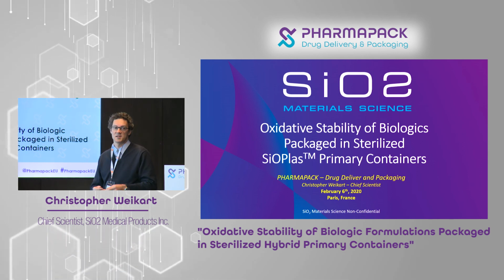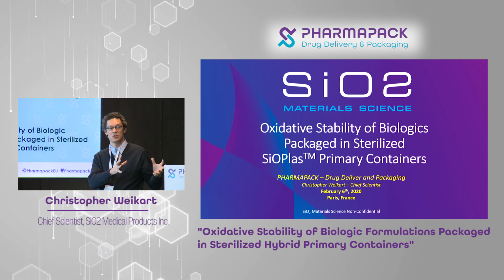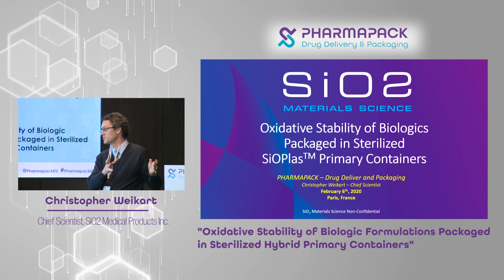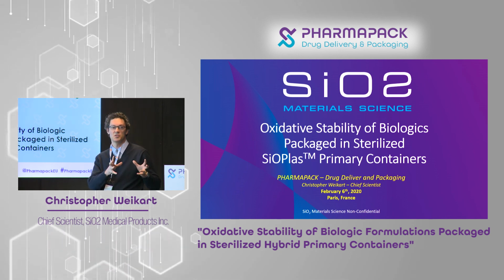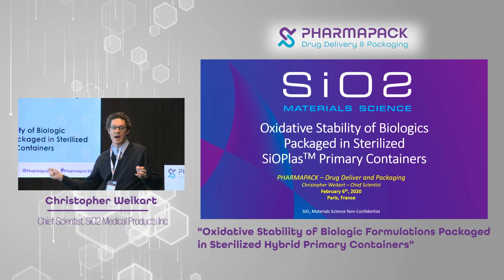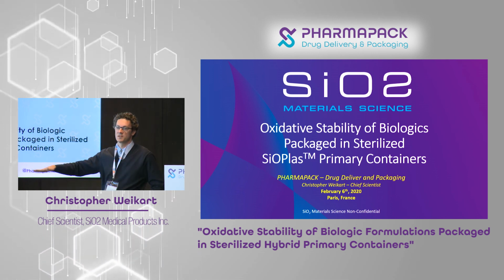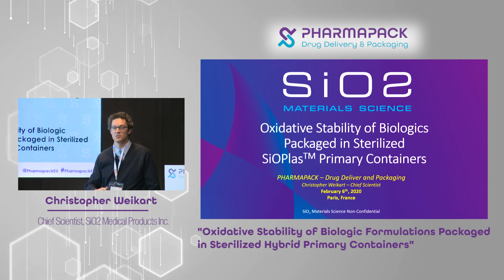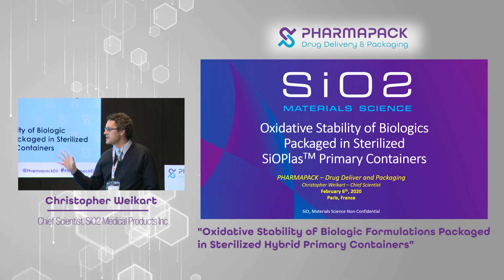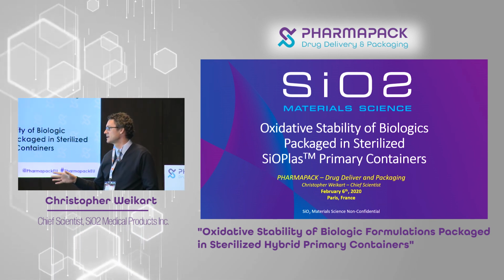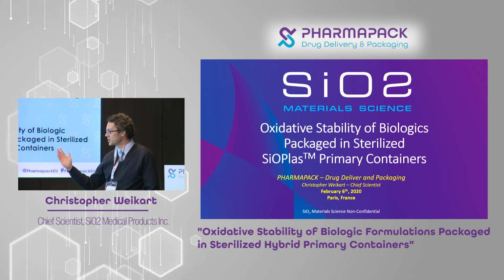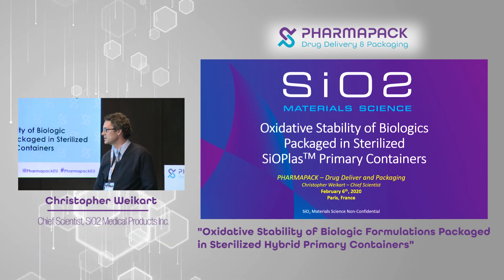And then there's another inspection that actually looks at barrier, believe it or not. So we've actually pressurized vials with CO2 and then pull the CO2 back out. And you're basically looking at desorption of CO2, and that correlates to the barrier. So we've got a number of systems in line with our manufacturing to ensure the coating's there and it performs as we would expect it to.